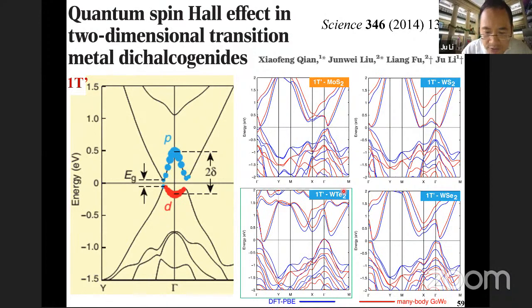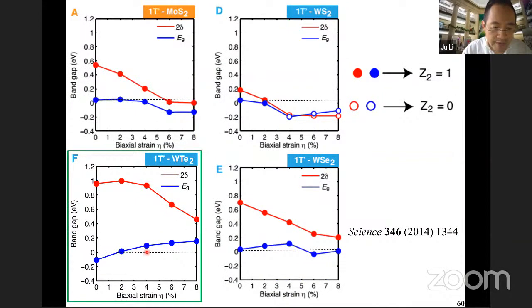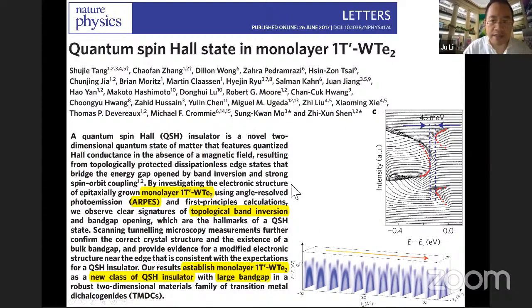But unfortunately, so you do open up this spin orbit coupling gap here. But unfortunately, it's also an accidental metal. So you actually need to have a little bit of strain, about 2%, to open up this accidental metallicity, but still preserving this fundamental band inversion. So in 2014, we predicted this T prime structure will be a topological insulator if you just apply a few percent strain. And that was indeed verified 3 years later by ARPES in monolayer.